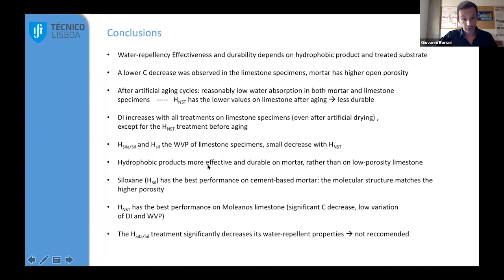And for sure, for example, in the case of the siloxane, which has a much longer chain, the molecular structure of this material is bigger when compared to silane. So usually those materials should be used for cement-based mortar, because you are looking for something that is penetrating in depth and matching the structure of this material.